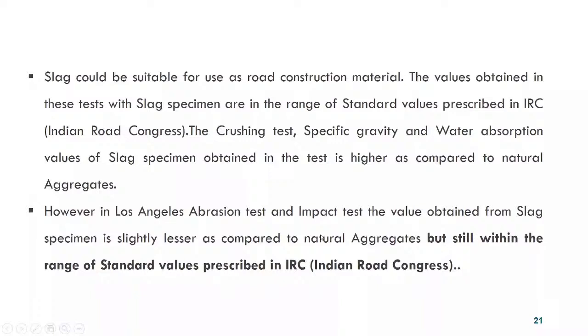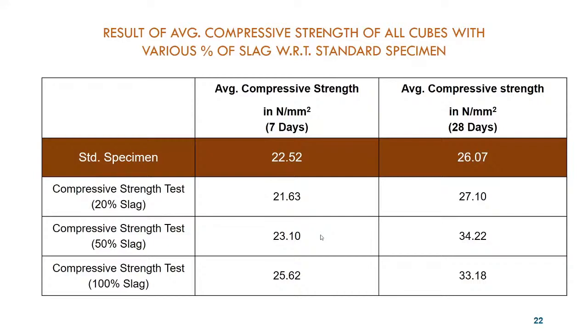So see, this is the result of the average compression of all cubes with different percentages of slag. The first one was the standard specimen, and the average compressive strength here is for 7 days and 28 days. Now this is for the 20% replacement of the slag, this for the 50% replacement, and this for the 100% replacement of the slag. See, the average compressive strength was higher for the 28 days, in comparison with the standard specimen.